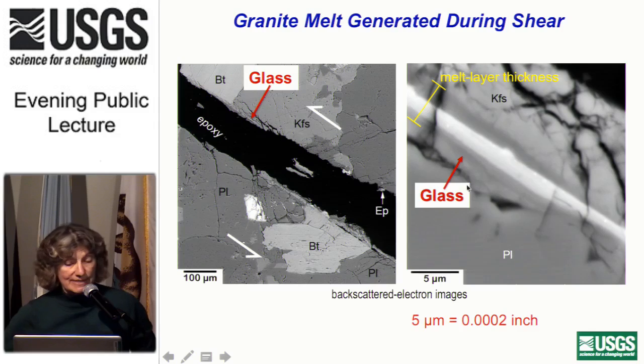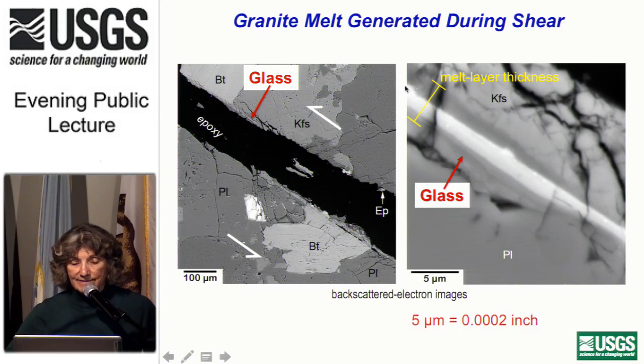And the slide on the right here shows a closer view of the fault plane. The yellow bar here and in the next couple of photos indicates the thickness of the melt layer. And we can see it's basically a solid line here. The boundary is just completely glued together when it quenched. So the thickness of the melt layer here is about 5 microns, translated to inches at the bottom here. But even in that very narrow band, we can see a lot of compositional zoning. With the backscatter electrons, as Leslie said, you get chemical information. So this bright band in the middle here is iron-rich, and it also has other elements in it that indicate that it's derived from the mineral biotite melting, and we'll get to that again later on.